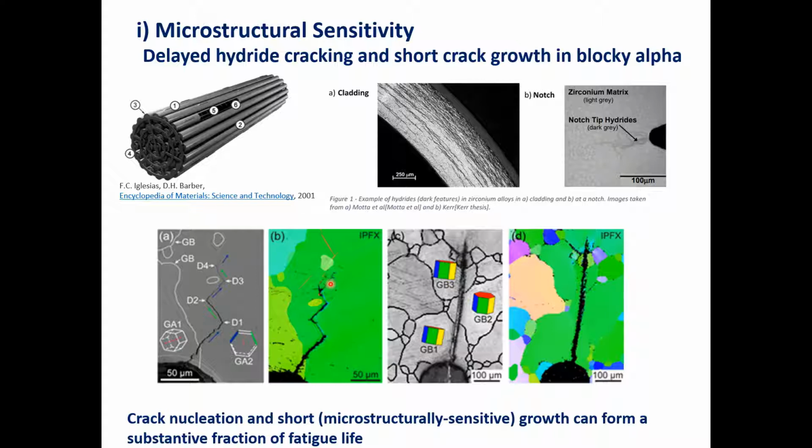If we look at the same loading conditions, but a very different sample with a different microstructure, this time organised with the HCP hexagonal grains organised such that their C-axes are parallel with the growing crack, then the crack seems to remain largely straight and parallel with the prism planes, but growing in a direction which is therefore perpendicular to the prism plane Burgers vector. In this case here, the cracks appear to be growing parallel to the prism planes, but in parallel also with the Burgers vector. These grains, with respect to horizontal loading, are well aligned for slip, whereas these grains are less so.